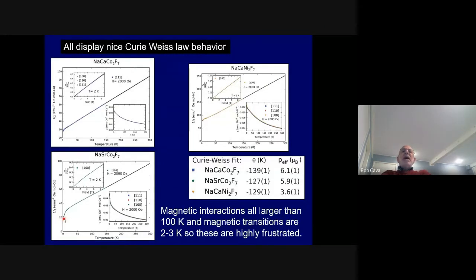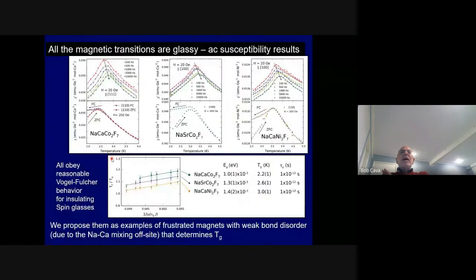Now, I am pretty sure that if we didn't have to get charge balance by mixing these atoms on the A site, like sodium and strontium, which are different from each other, they induce a kind of weak disorder into the system. They're not on the magnetic lattice. They are bonded to oxygen or fluorines that are in turn bonded to the magnetic atoms. And that gives rise to some kind of disorder in the system that's weak. And they become spin glasses at low temperature.